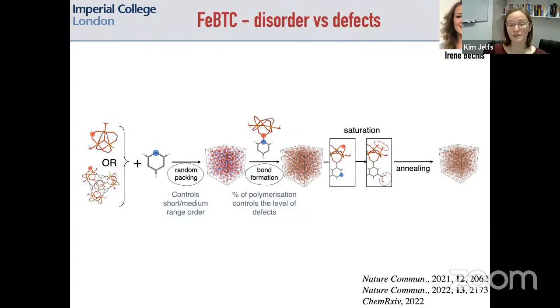So we're using some software called Polymatic, developed by Coray Colina's group in the US, and I have a reference for that on a later slide. But essentially, Polymatic works by doing a random packing of your monomers, and then doing loads and loads of rounds of bond formation to polymerize the structure, and then you do molecular dynamics procedures to anneal the structure at the end, and you make sure that you've capped any unreacted end groups.